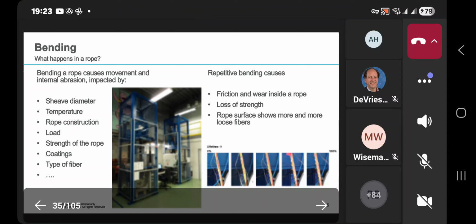And there are several parameters that are impacting this number of cycles. For example, the sheave diameter, if it becomes smaller, it is more severe, you will get less cycles to failure. Temperature has a negative impact. Load higher means less number of cycles. And also we know that the friction between the different fibers plays a role. So we have developed coatings on fiber and rope level to improve that performance.